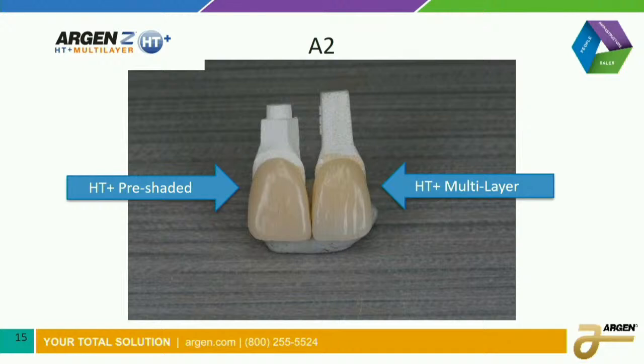So with the multi-layer, what we do is we have different compositions, and in our case, we have 5 different compositions that get molded together. And the gingival has a darker, or larger amount of coloring oxides than the incisal, and then we vary the coloring oxides in the material as you go from the gingival down to the incisal. Okay.